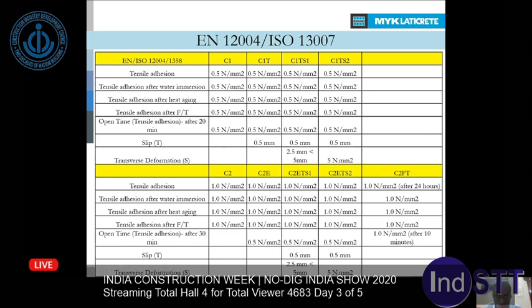And again, when you have mosaic or highly vitrified or low water absorption tiles, we recommend going with the C2. And again, based on your application requirements, you can select any one of them. Suppose you want to fix a tile on the exterior, on the large format, with a lot of movements, then we recommend going to C2, extended working time and non-slip, and highly deformable S2. So that's how the standards are available, and based on that, you can certainly demand from the manufacturers, okay, I need this, and they can provide the material that meets all these conditions.